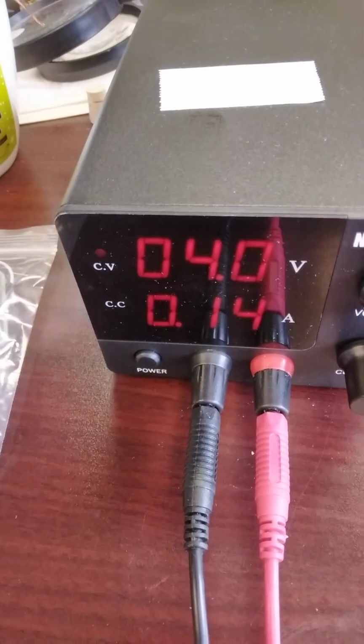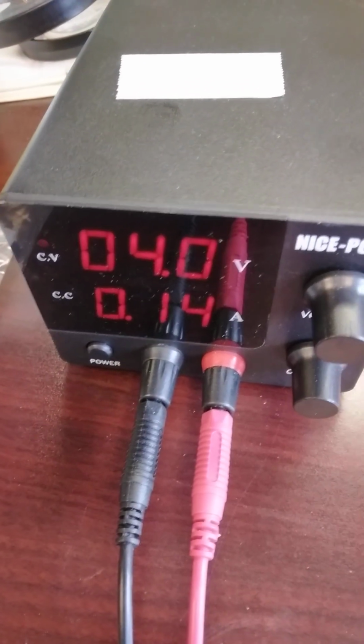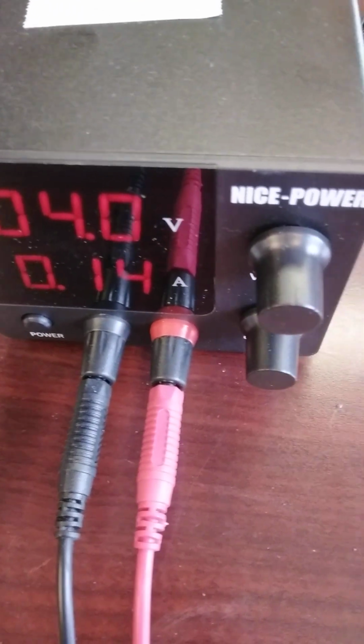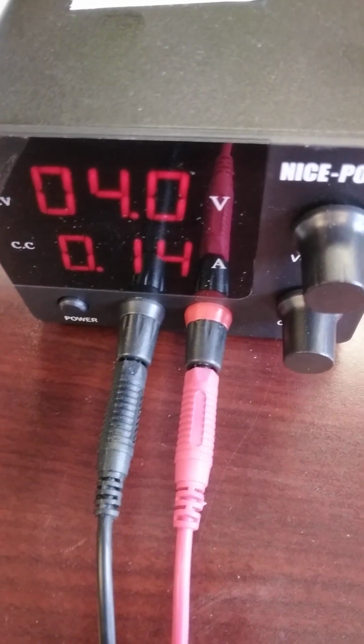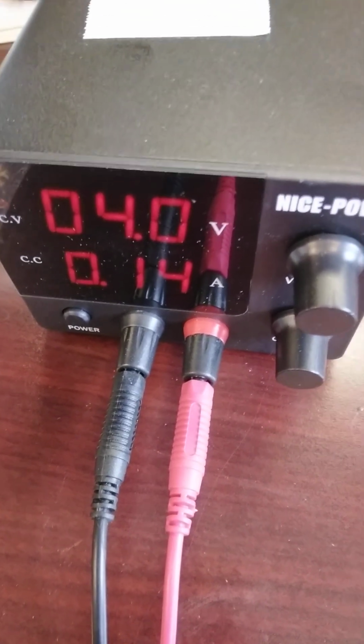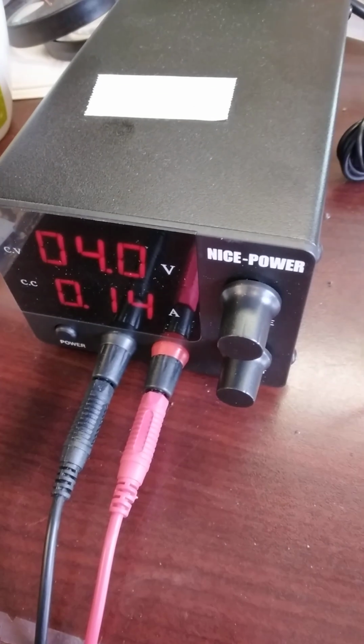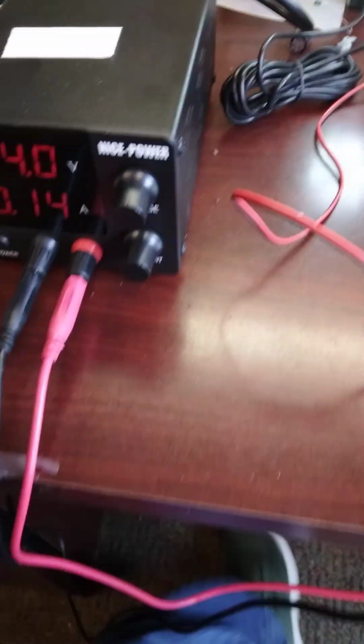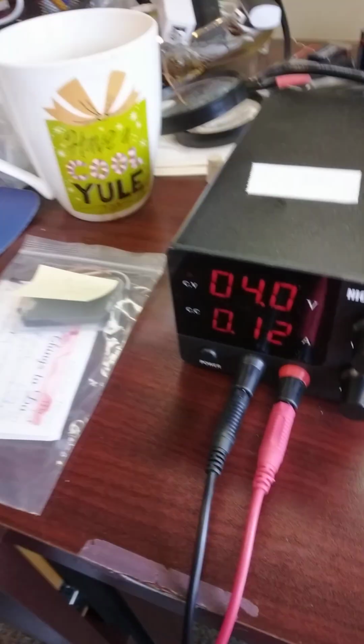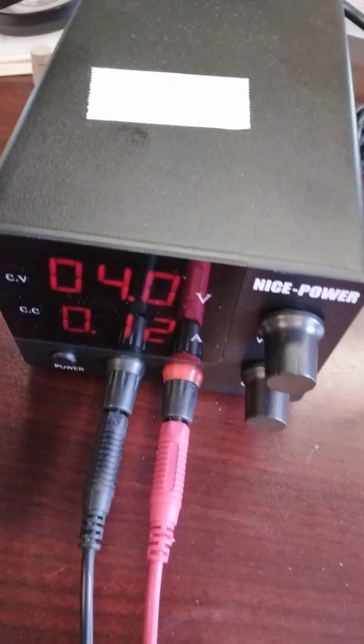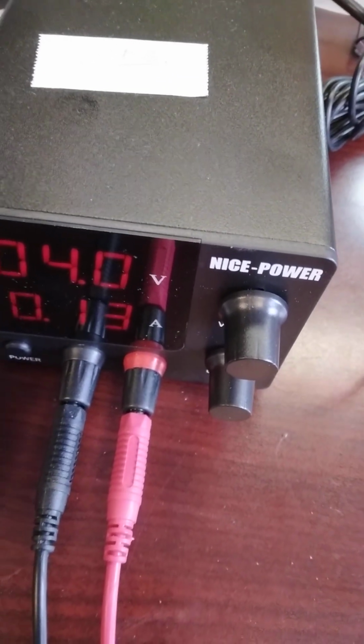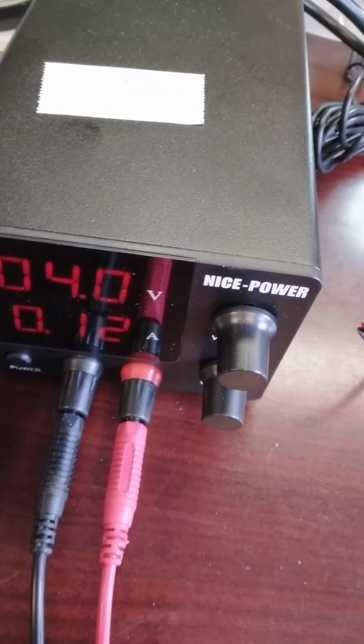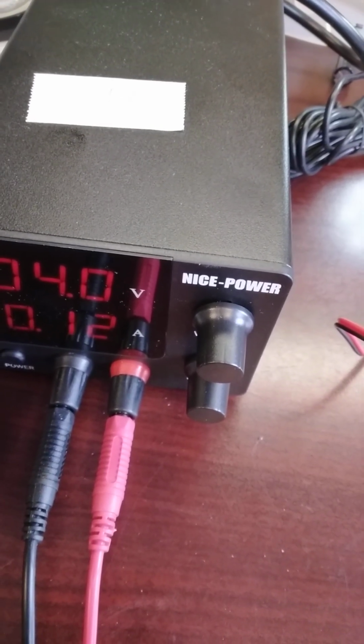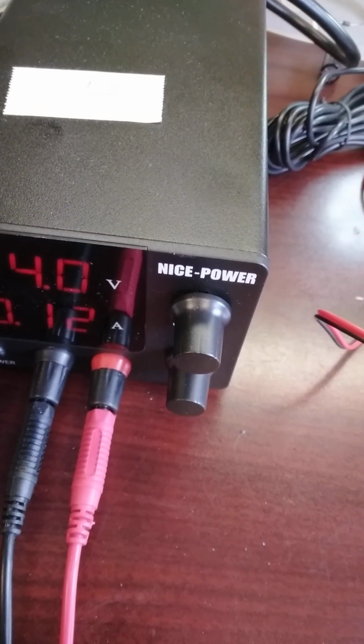And why do we want to use constant voltage here versus constant current, which I was doing before? Notice it's at 0.14 right now. So we'll keep an eye and see what's going on early on. It makes more sense to run the experiment at a constant voltage, let's say 3.7 to 4.0 volts, and observe the current changes as an indicator of the DES solvent chemical changes or evaporation, especially for certain types of degradation mechanisms.